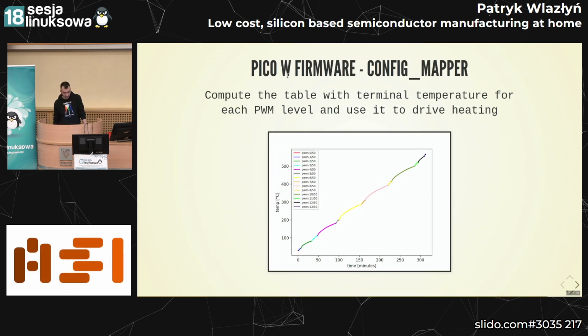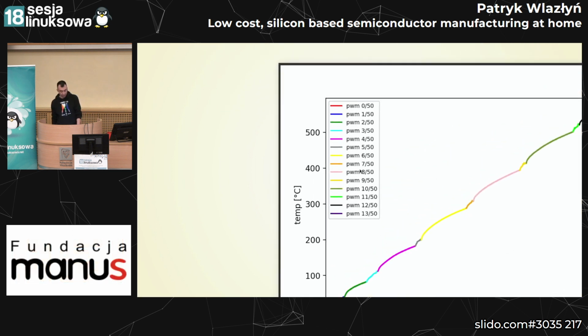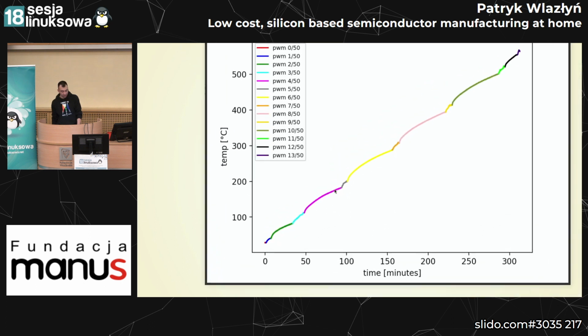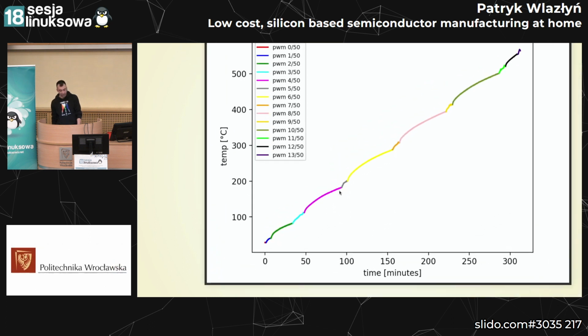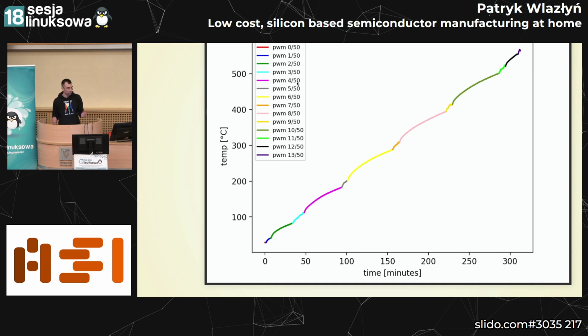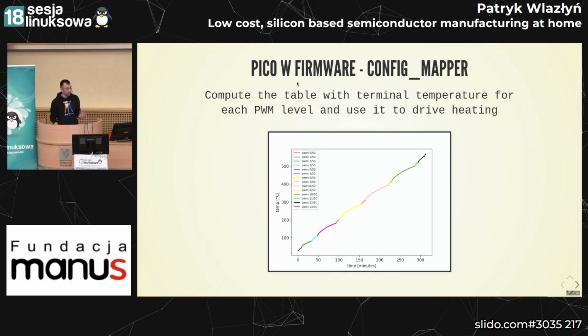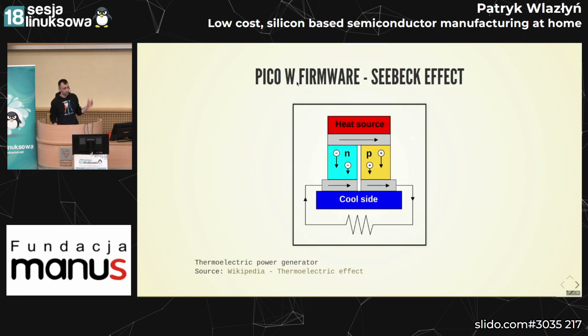We also have a way to pre-compute a table for each PWM level to say what is the terminal temperature that can be reached on a given PWM and drive the furnace with this. So for example, here for the PWM level of 4, we can see that the terminal temperature that we can reach with this level is around 200 degrees C. So we know that if we want to reach 200 degrees C, it's probably good to just set PWM to 4 and basically wait. So this is another way of steering the furnace, and it works better than PID.